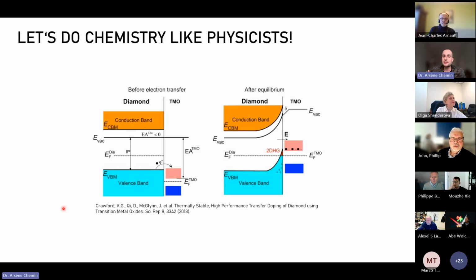So in the physics of semiconductors, every time you put together two semiconductors, you will have a mismatch of the Fermi level between one and the other, and that will lead to a charge exchange. So you will have electrons going from the semiconductor having the highest Fermi level to the semiconductor having the lowest Fermi level. And this will lead to a charge depletion layer and band bending. So basically you will have positive charge on one side, negative charge on the other side. That will create an electrical field that will compensate the initial mismatch in energy between the electrons.